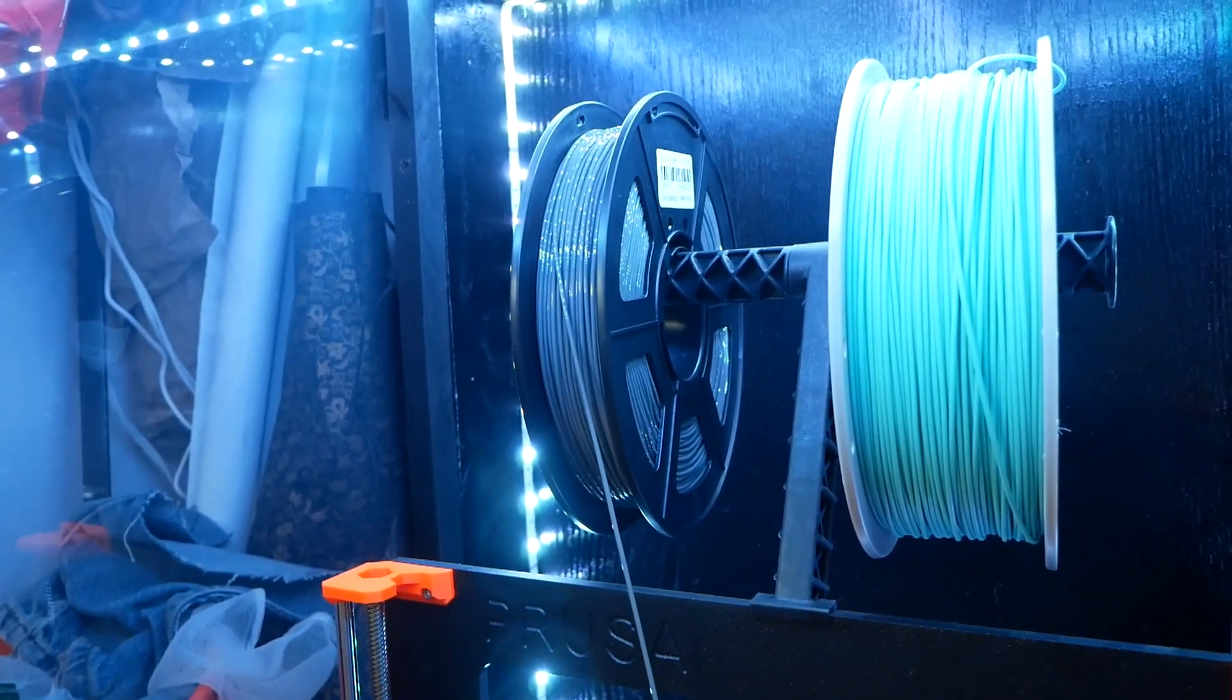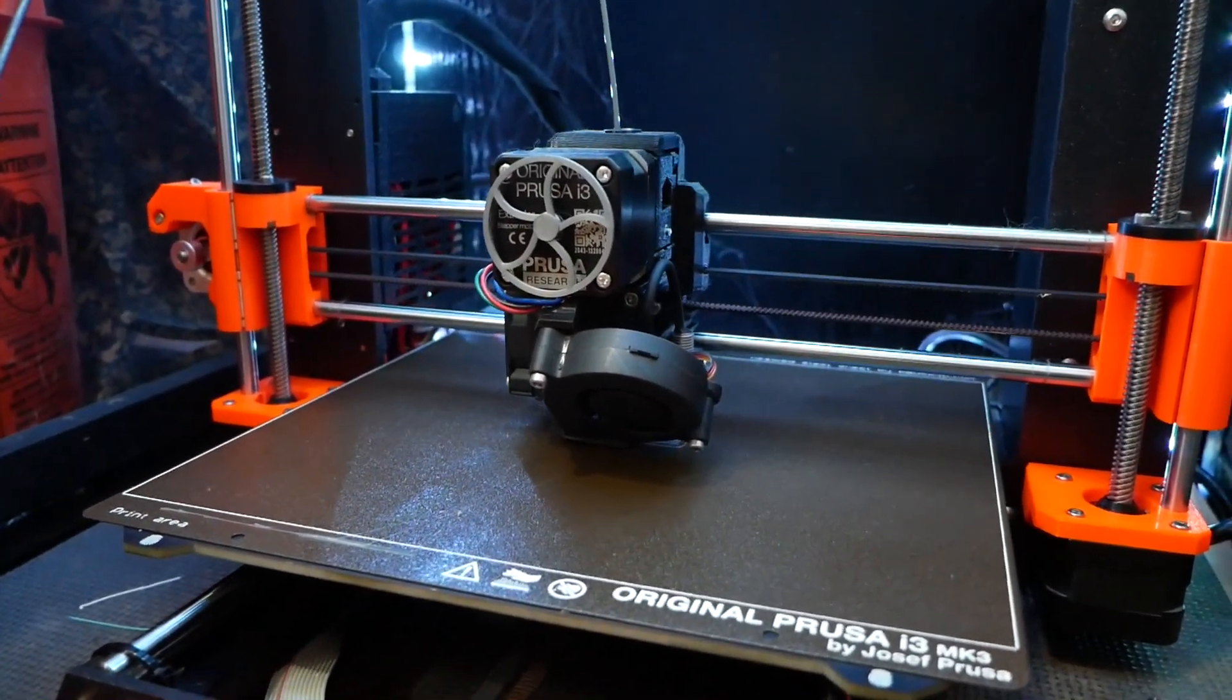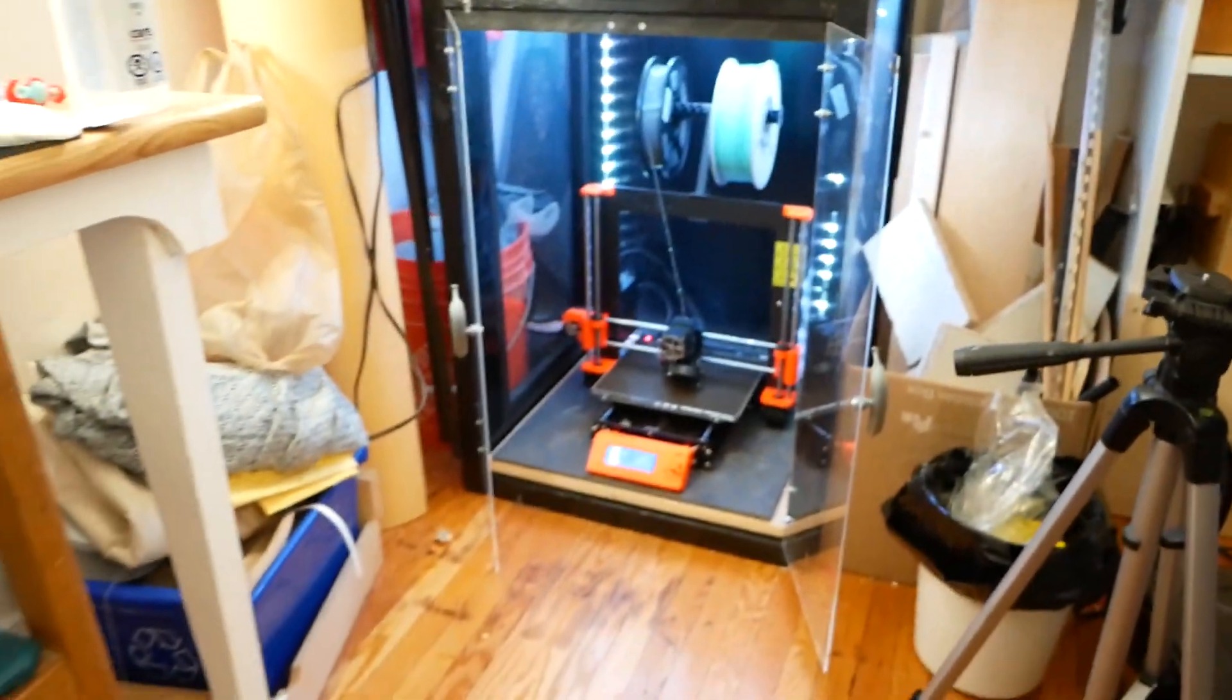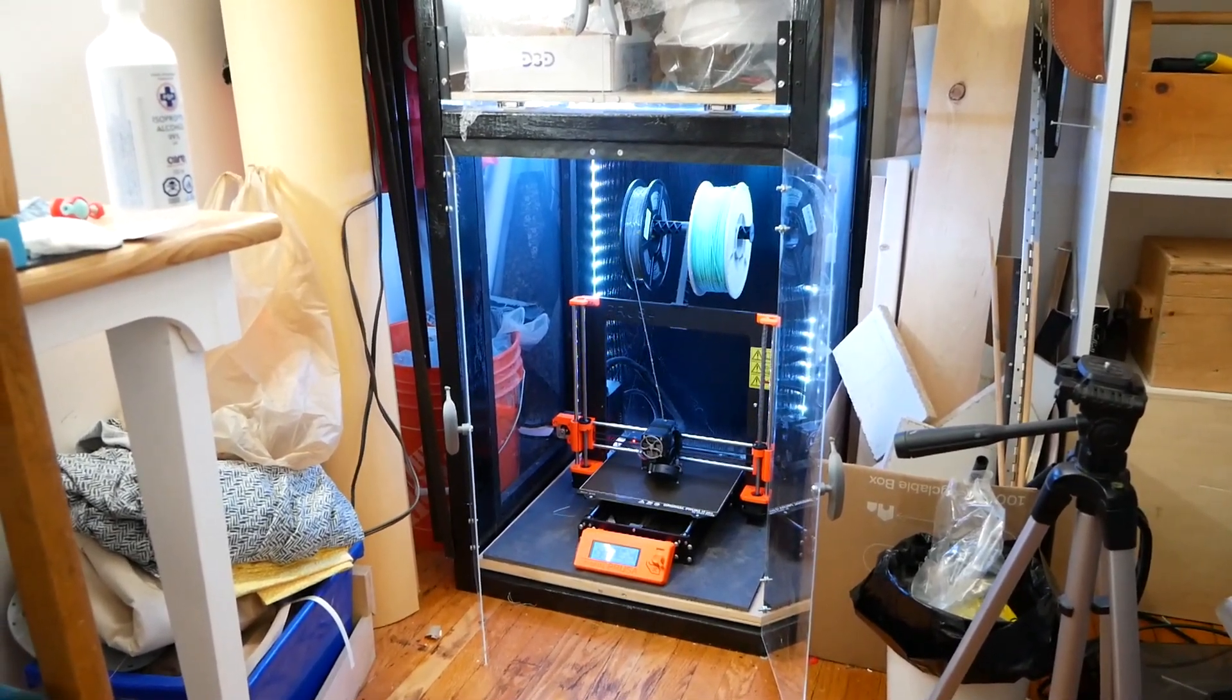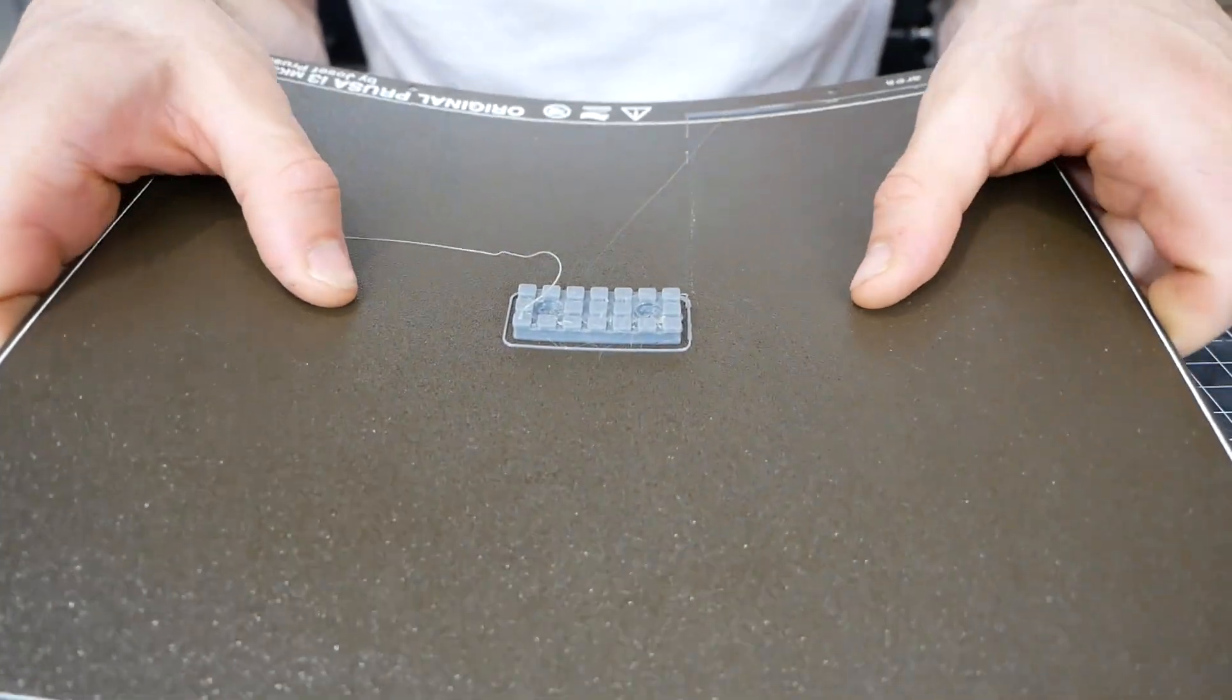And I think that's pretty much it. Let's go print. We're printing this with D3D Sigma TPU. This stuff comes in 500 gram spools, which is really handy because TPU is expensive. So if you just want to try this material out, you don't have to commit to a whole lot of it at once. I'm printing it on the textured sheet on my Prusa i3 MK3S. TPU adheres super well to the textured sheet, but if you print this on a smooth PEI coated sheet, you should use tape or glue because you can damage the plate when you remove your final print. As you can see, I have the doors to my enclosure open. I found that when the doors were closed, small details weren't printing very well - they were getting really muddy. I think that's because the filament didn't have enough time to cool as the nozzle was moving around. Print is done.